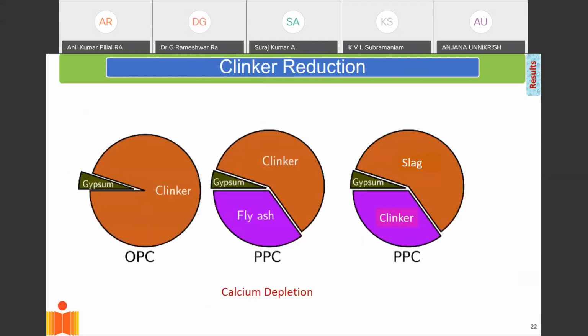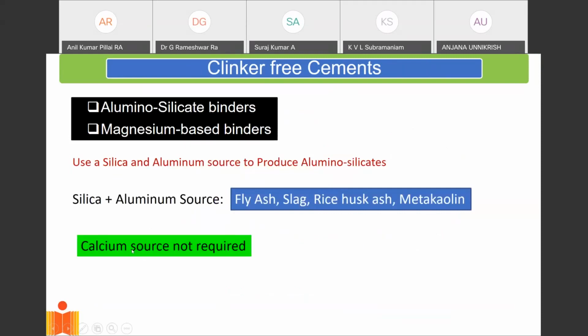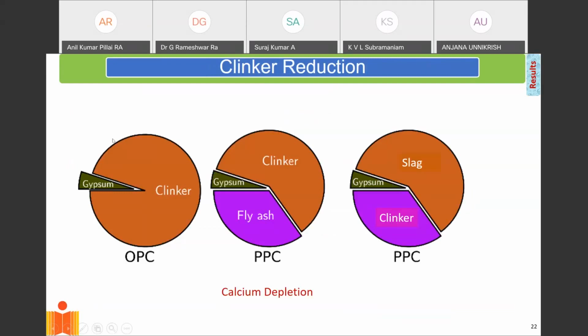Now, this is already in practice, like I mentioned. So if you look at ordinary Portland cement, clinker is basically what comes out of the kiln. When I burn limestone and clay together, I produce clinker. And it is ground with gypsum, and this is what we get as ordinary Portland cement, OPC. But now already in the market commercially, clinker is interground or mixed with fly ash, and it's available as PPC. We also add slag with clinker, and that's also available in the form of Portland pozzolana cement.